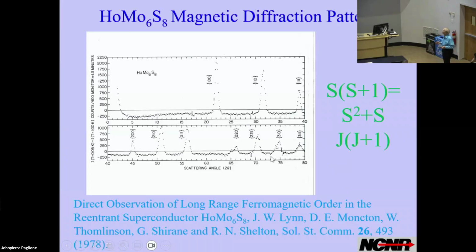How do we actually study them? Two different ways. One is to do the diffraction pattern to see if it looks like a ferromagnet. And this is the simplest type of ferromagnet you'll ever see. You see the Bragg peaks like here, 100, 110. I just index them according to a cubic cell. This is actually rhombohedral, but you can't tell the difference here. And there are a couple of things to notice about that.